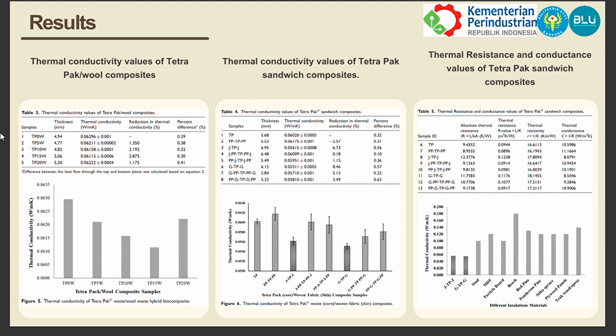Okay, we move to the next slide. This is the result. Figure 5: the thermal conductivity of Tetra Pak wool composites. The thermal conductivity decreases as wool content increases, reaching the lowest value at 15% wool, around 3% lower than 0%. The improvement occurs because wool fibers create air voids that trap heat. A slight increase at 20% may result from fiber agglomerations.